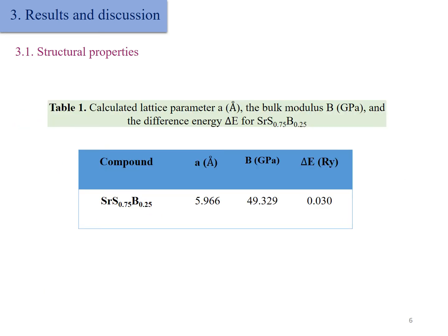The given optimized lattice parameter, the bulk modulus, and the difference energy for our compound are illustrated in Table 1 for visualization, in which it is clear that the positive sign of ΔE confirms the stability in the ferromagnetic phase.